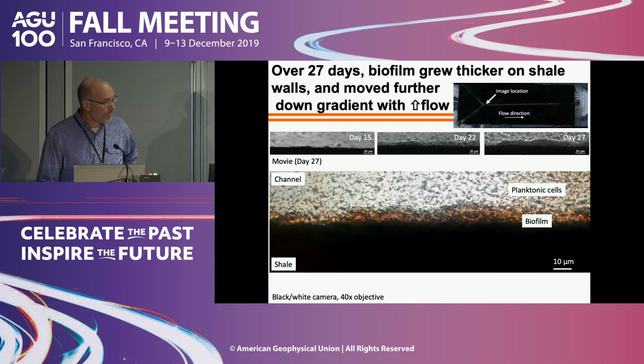One thing we observed that's not apparent in the pictures is that as we increase the flow rate, the length of the biomass, or how far it grows down gradient from the mixing point, increases. That's because we have limited nutrients, and so basically it's a trade-off between the rate of advection and the rate of reaction. If you assume everything's uniformly mixed here, the higher the flow rate, the farther down gradient the nutrients will get before they're consumed by the biomass. And so as you increase the flow rate, we would get more and more biomass growing down gradient. So that was kind of cool. We haven't started to model this yet, but we want to look at these rates of growth relative to advection on this shale with that data.